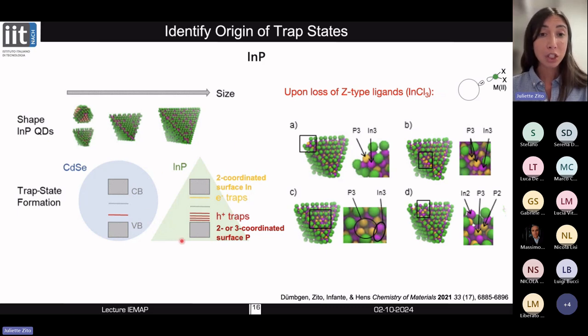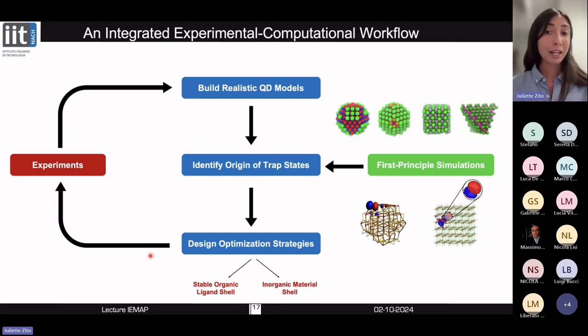So these materials were found to be much more sensitive to the formation of trap states than, let's say, the well-known cadmium selenide quantum dots. But now let's come to the final step. Once we have identified the origin of trap states, we also need to design optimization strategies.